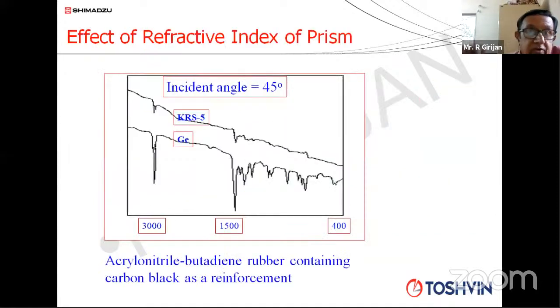Then the effect of refractive index. The refractive index of the crystal should always be more than the refractive index of the sample. Please keep that in mind. Any sample containing carbon black has a very high refractive index, somewhere around 3.6 or 3.7, roughly more than 3. Most of the crystals have a refractive index less than that. And if the refractive index of the crystal is less than that of the sample, you will get a very bad quality spectrum.